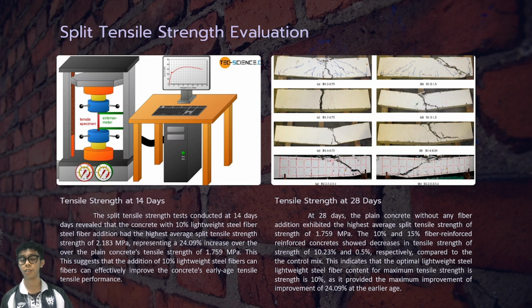Split tensile strength evaluation. Tensile strength at 14th day. The split tensile strength test conducted at 14th day revealed that the concrete with 10% lightweight steel fiber addition had the highest average split tensile strength of 2.183 MPa, representing a 24.09% increase over the plain concrete tensile strength of 1.759 MPa. This suggests that the addition of 10% lightweight steel fiber can effectively improve the concrete early age tensile